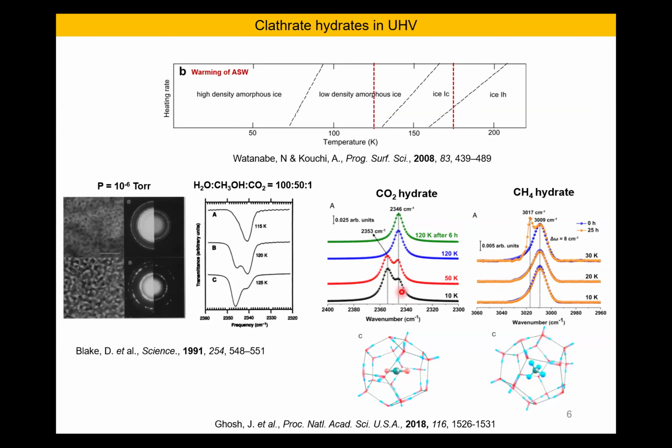This is very important because infrared spectroscopy can only suggest the molecular environment where the molecule is confined, or whether it is in the amorphous solid water, through the peak shift. You can say the molecule is inside the cage by comparing with the reference and some control experiments. But with the diffraction experiment, the exact crystal structure remained a question.